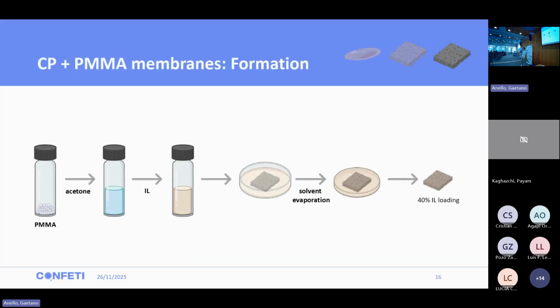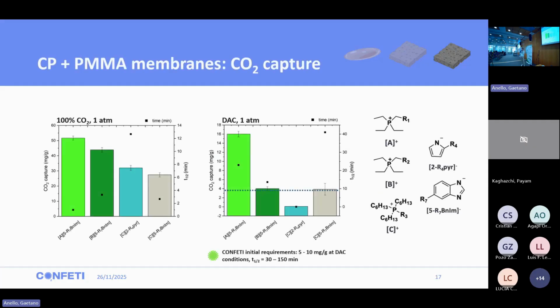So the idea of this approach was to keep the physical chemical properties of the previous material, but avoiding the ionic liquid leakage. To do that, we just dissolved polymethyl methacrylate in acetone, we mixed with the ionic liquid, and we put it in a beaker with the carbon paper, and we let the solvent evaporate, achieving a 40% of ionic liquid loading. So the idea was to form this polymeric matrix inside the porosity of the material. With this technique, we were only able to obtain 4 of the 6 materials of the previous one, because with the pyrrolate, we were not able to form the membranes without reducing the amount of ionic liquid in the material.